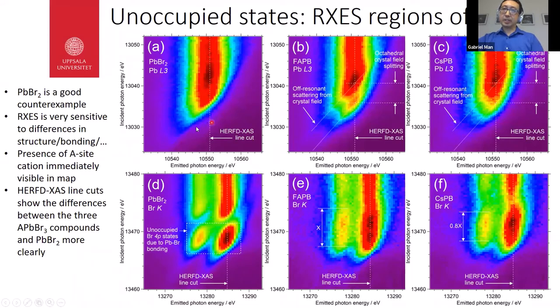First of all, we can see that the off-resonant features look very different. For formamidinium lead bromide, we can see these crystal field features, which we can also kind of see in cesium lead bromide, but they're not as distinct. So that's already telling us that there are structural differences that we can probe.